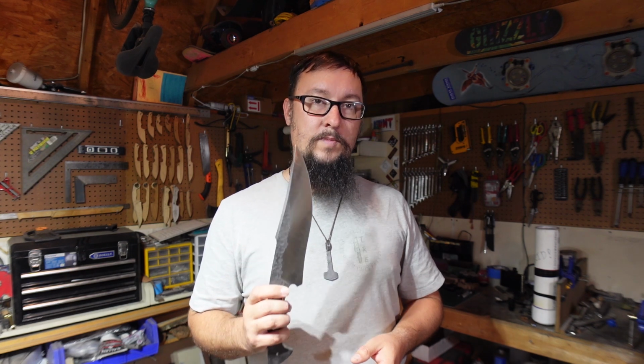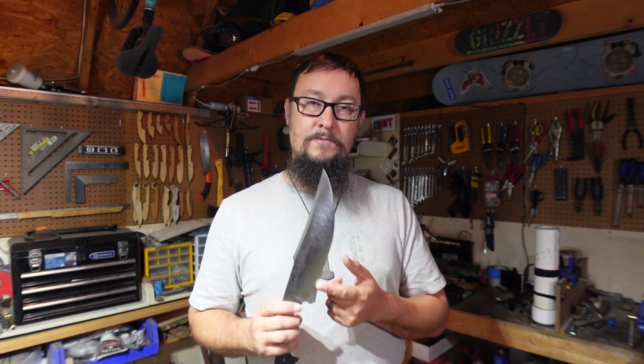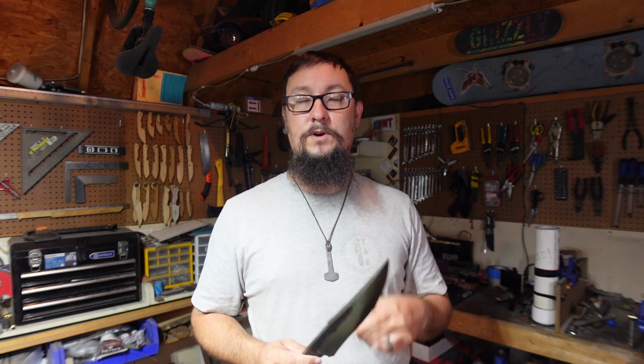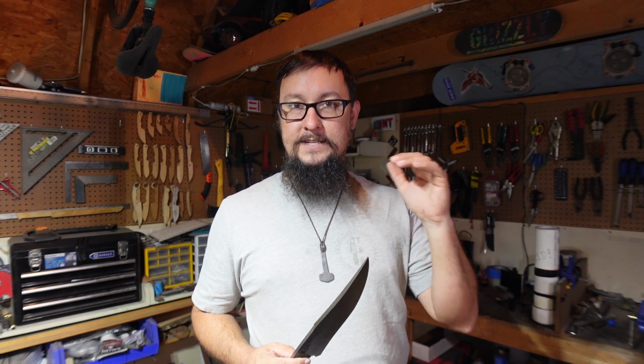But for me, I have a process, I know what that process is going to be, and that's what I tend to do. Now, I'm going to be doing my normalizing cycles with this steel. We're going to do 3 rounds of normalizing. We are going to bring it up to about 1575 to 1600 degrees, and then we're going to let it air cool. Then we're going to bring it back up to about 1525, let it air cool, then we're going to bring it back up to about non-magnetic, so between 1420 to 1450 degrees, and we're going to let it air cool.